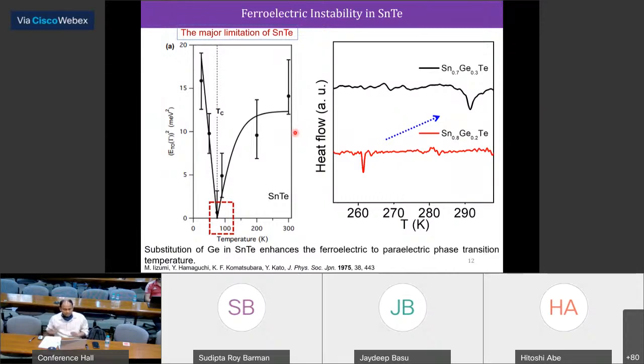So in order to do that, we have purposefully doped germanium, because germanium sits just above the tin, so it will have a much more active 4s2 lone pair than tin. So we have doped around 30% of germanium. We showed the phase transition temperature shifts near to the room temperature. So that is our first goal.